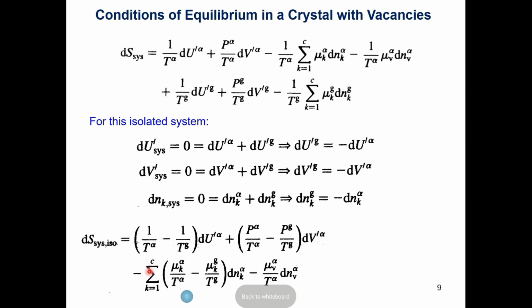So by design, because of the criterion of equilibrium, this is going to be zero, this is going to be zero, this is going to be zero. But you know that entropy change in an isolated system reaches a maximum—there is no further change, and the system is in equilibrium. So DS, the change in entropy, has to be zero. For this term to be zero, there is no other choice but to say that the chemical potential of vacancy in your solid has to be equal to zero. Otherwise, we would violate the second law of thermodynamics.